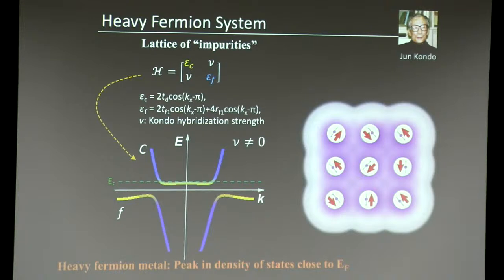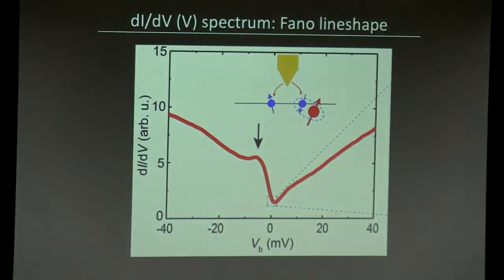So now let's do STM spectroscopy and look for the sharp peak in the density of states at the Fermi energy. And this is what the STM spectrum looks like. By no means is this a sharp peak in the density of states. It has a very strange line shape, with a small peak here and a large dip here.